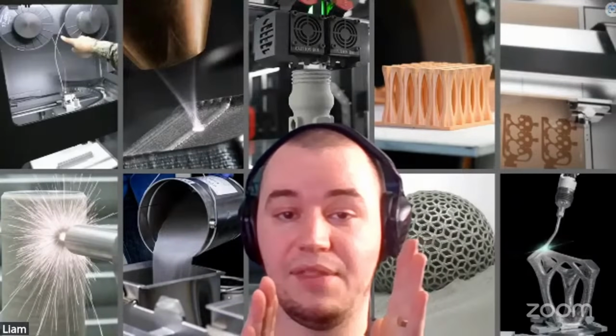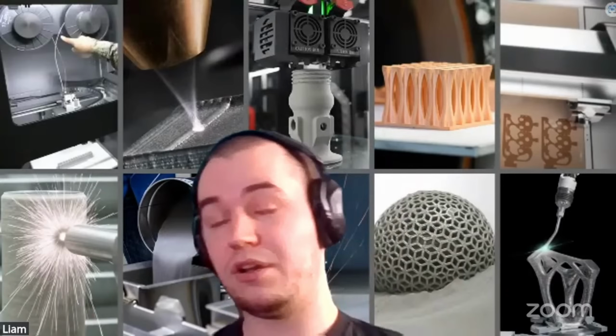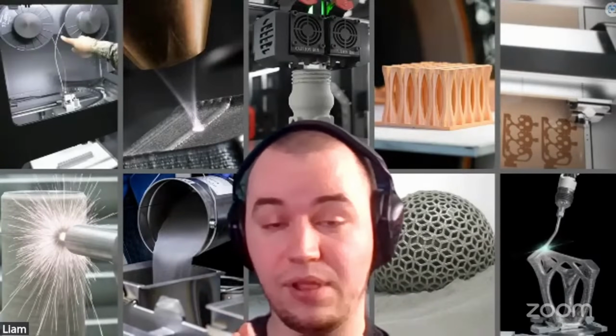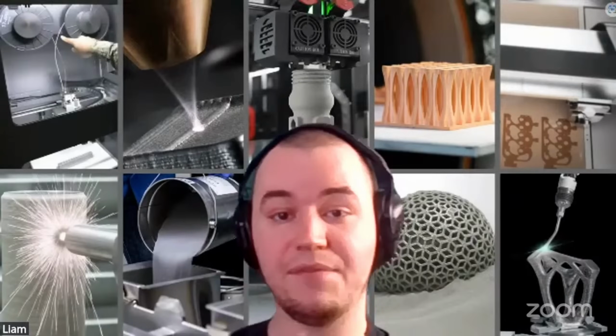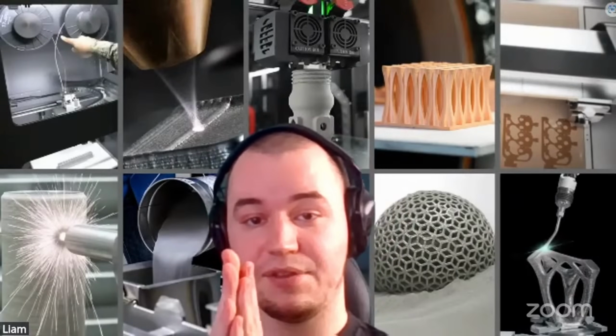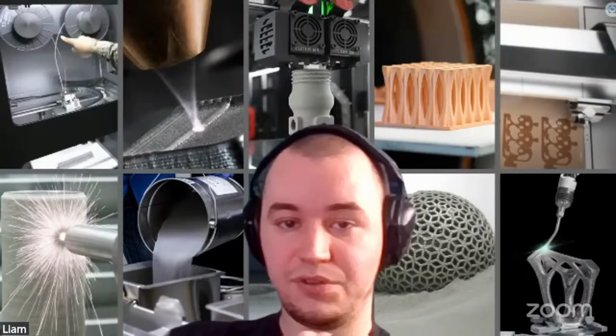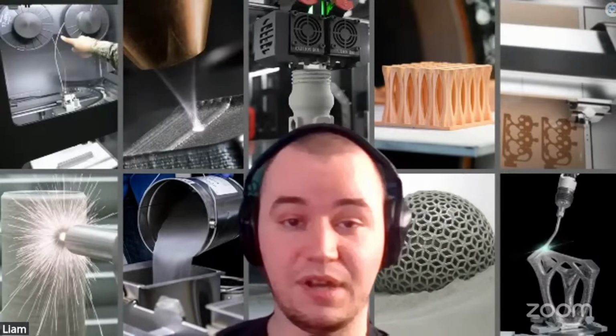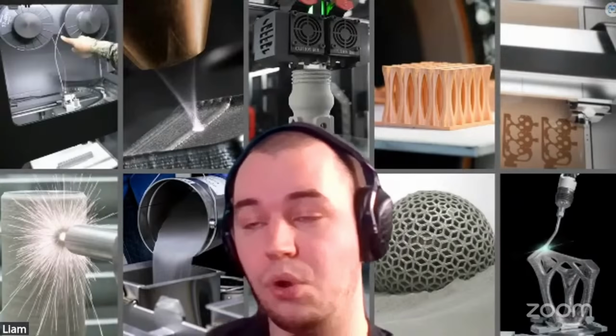And so if I wanted to cold weld titanium to titanium, one way of doing that is, and this sounds kind of silly, you can take two very smooth, clean titanium surfaces and put them in an oxygen-free environment, such as under argon gas, and then clean off the oxide layer either with a chemical etchant or mechanically by using a blade to scrape off that top layer. Then you can slide them together or just press them together and wring out the trapped air, the trapped argon gas, which is non-reactive, and you will have a decent cold weld there.